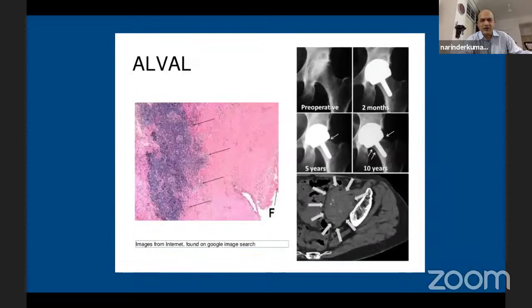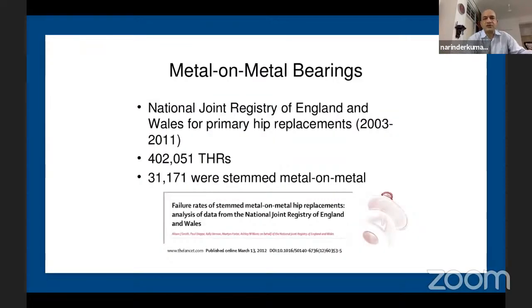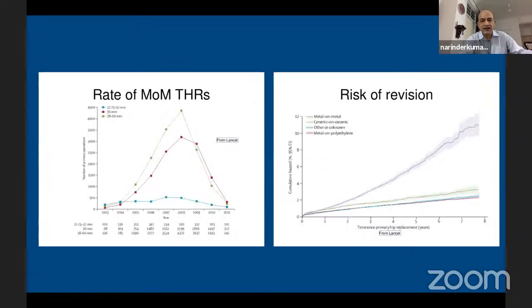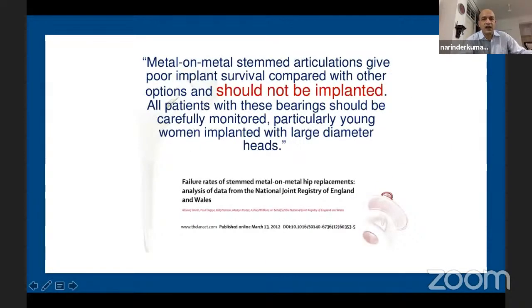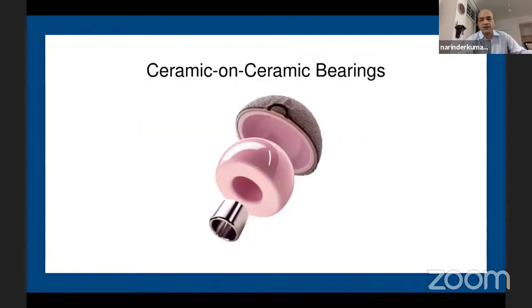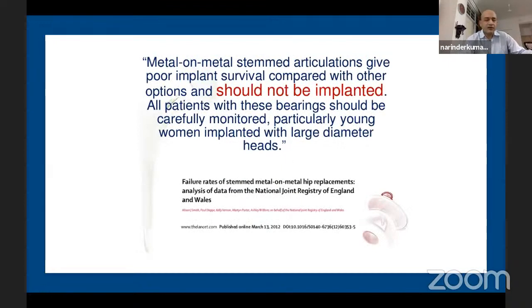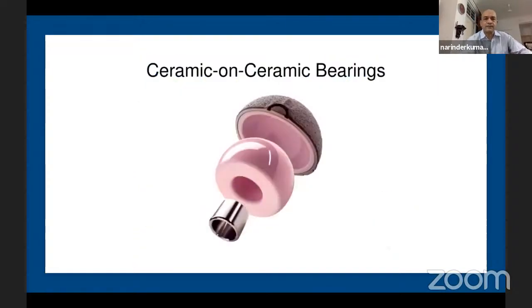I won't go into the details of this osteolytic lesion, but the National Joint Registry of England as well as the Australian Joint Registry came out with data showing a huge risk of revision at 5, 6, 7, 8 years - catastrophic failures. So the rate of metal-on-metal total hip replacement dropped after that, with registries recommending these should not be implanted. And DePuy and a lot of other companies are still paying for it even a decade after they stopped implanting these, because of litigation issues.